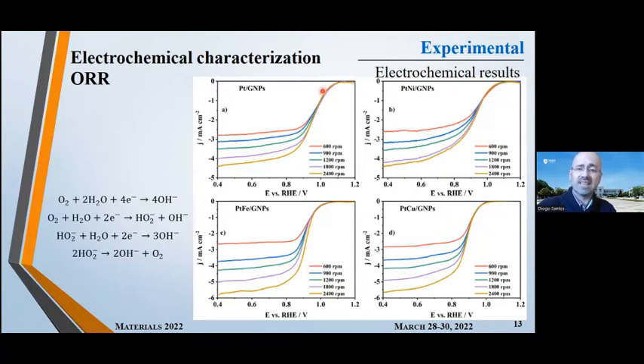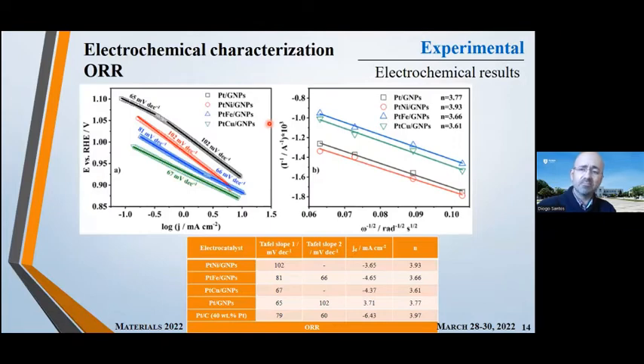Basically, what we do is scan the potential at a fixed scan rate of 10 millivolts per second, and then we do the experiments at different rotation rates. So we increase the rotation of the disc electrode, and we have increasing currents. We have done this for these four materials, the alloys and just platinum, and then based on the results, we are able to plot the current that we obtain at a fixed potential value as a function of the rotation rate of the electrode.